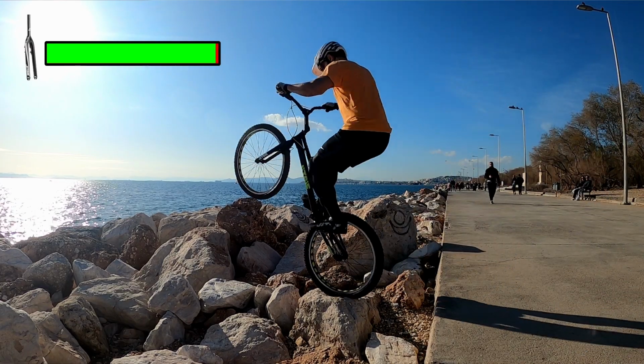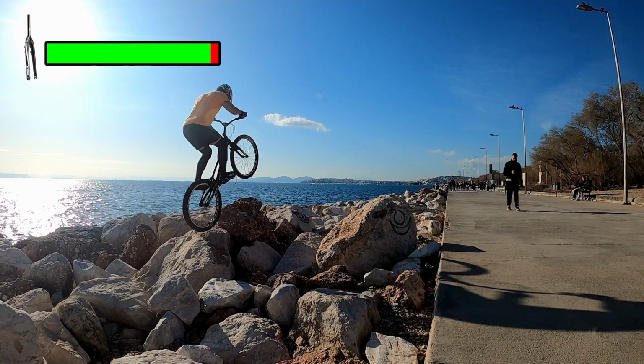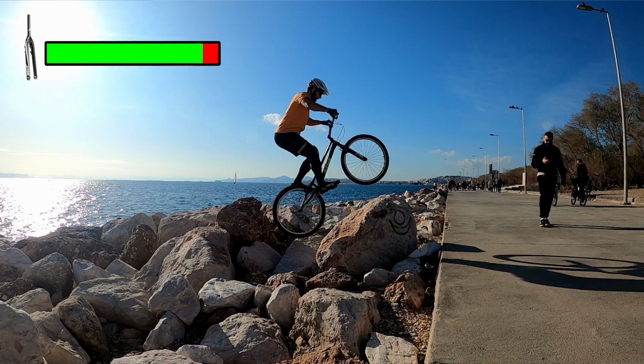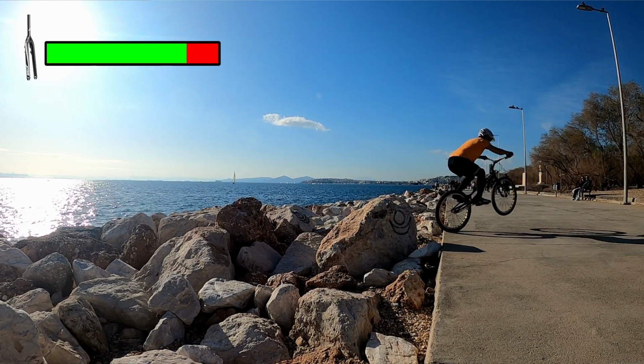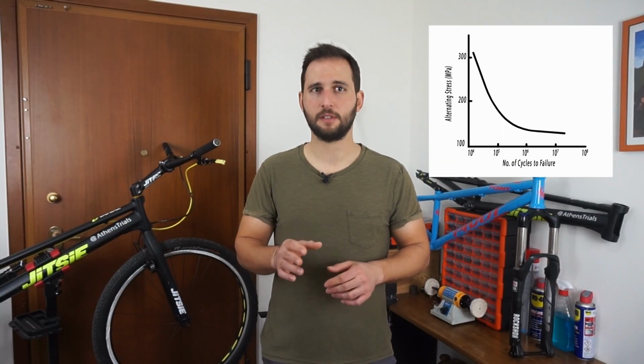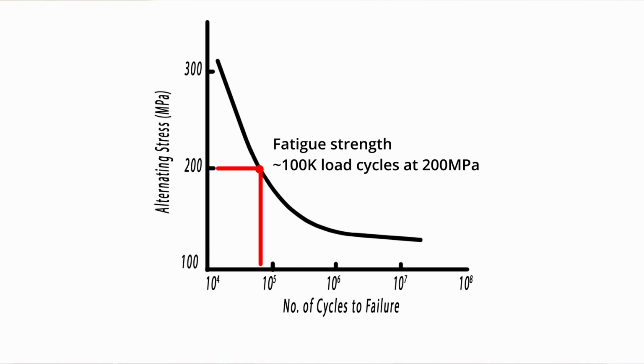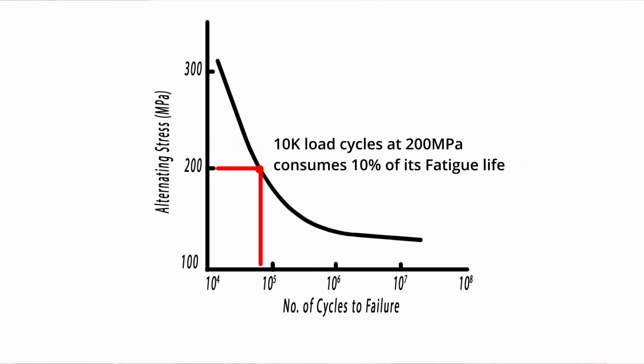According to the Miner's rule, each load case consumes a proportion of the part's life as a percentage of the total load cycles considering the specific load magnitude. So, picture that every time you ride, you consume a different proportion of any part's life during any move you make, up to the point that the part fails. For example, loading a part made out of 7075 T6 aluminum alloy so as to get stressed at 200 MPa for 10,000 cycles would mean that 10% of the fatigue life has been consumed for this part and the rest 90% is left for other load cases.